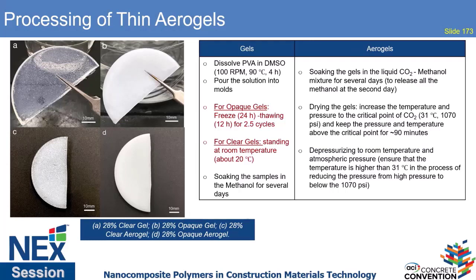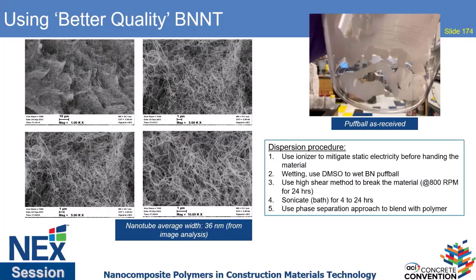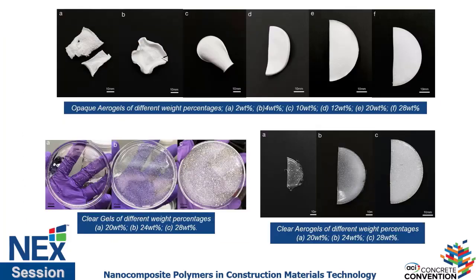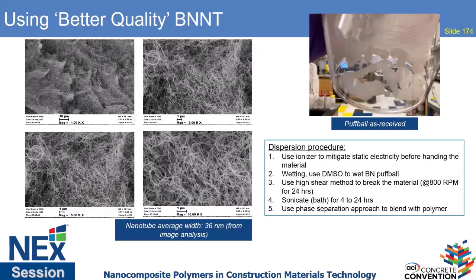And we're trying to make something that is lightweight, but also thermally insulating, and a better material than what we currently have, which is the silica aerogels that are very brittle. But the interesting thing is we're incorporating, in this particular case, boron nitride nanomaterials into these structures. And why we're doing that is one of the big things that we experience when you make an aerogel in the supercritical drying process is you get a lot of shrinkage and deformation. So what we're doing with these boron nitride nanomaterials is we're trying to reinforce the gel structure itself in order to make the gel structure a bit more mechanically robust so that it can go through the supercritical drying process and make a better aerogel using a very flexible polymer.